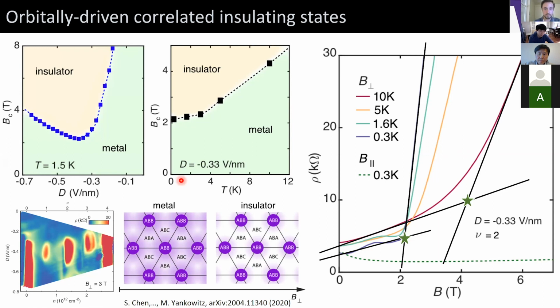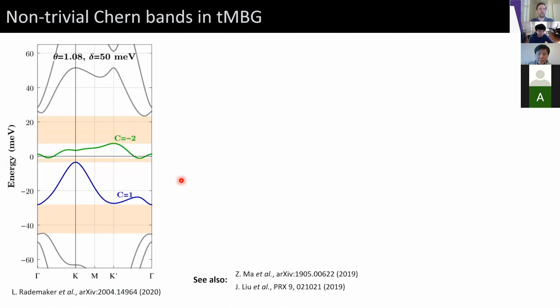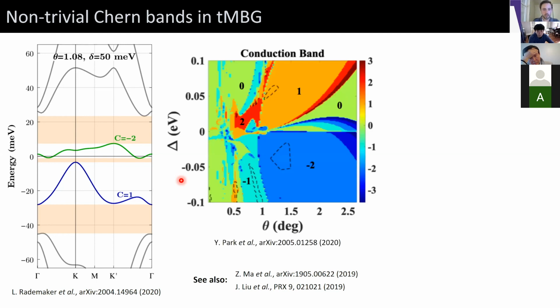Okay, so one thing that I haven't considered yet is that these bands actually have non-trivial Chern indices. And in principle, these non-trivial Chern numbers can lead to some sort of anomalous Hall effect. So there's been a number of calculations now for twisted monolayer-bilayer graphene that indicate that indeed these bands have non-trivial Chern number, and these can be tuned with electric field and also with twist angle. So this, in principle, is an interesting platform to search for the quantum anomalous Hall effect.